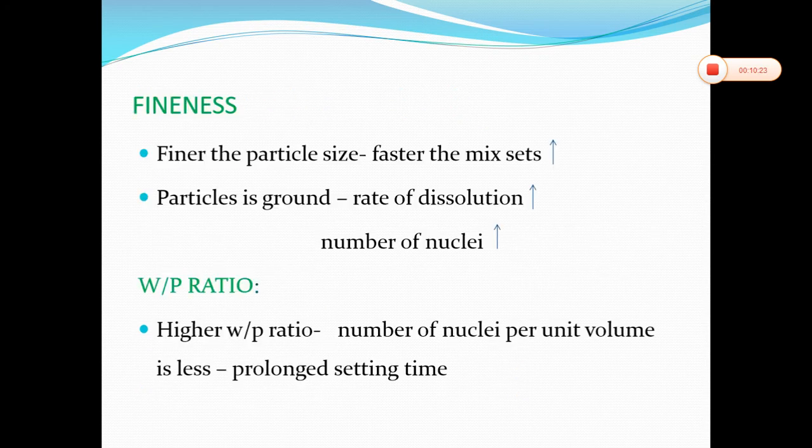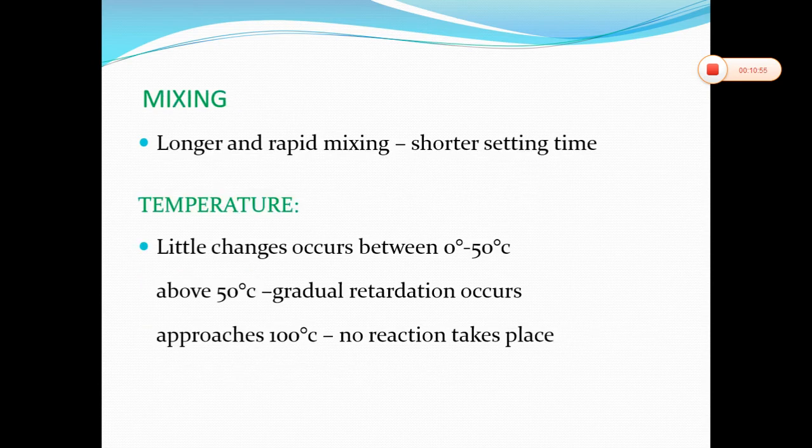Fineness. The particles of hemihydrate are fine when they are ground, when they are broken. If they are fine, the mix will set fast. When the particles are ground fine, the rate of dissolution is more and the number of nuclei is more, so the setting is also very fast. Water powder ratio, here we discussed. The higher the water powder ratio, the number of nuclei per unit volume is less. The fewer the nuclei, the more prolonged the setting time. It retards the setting.